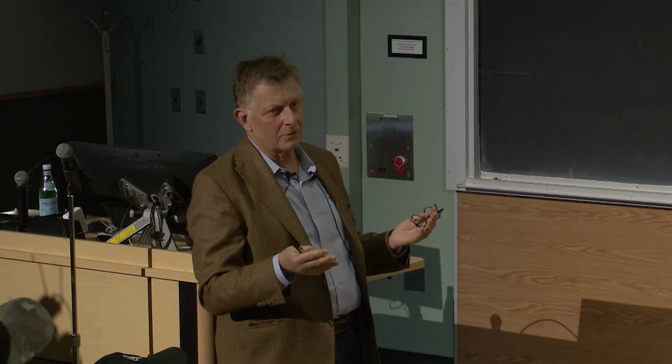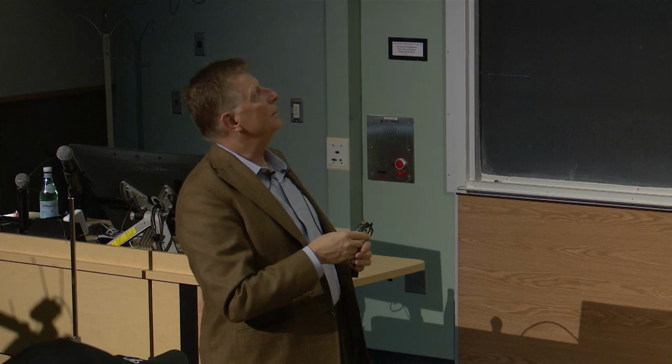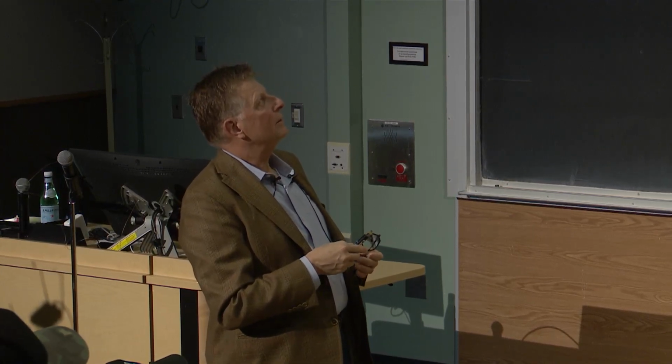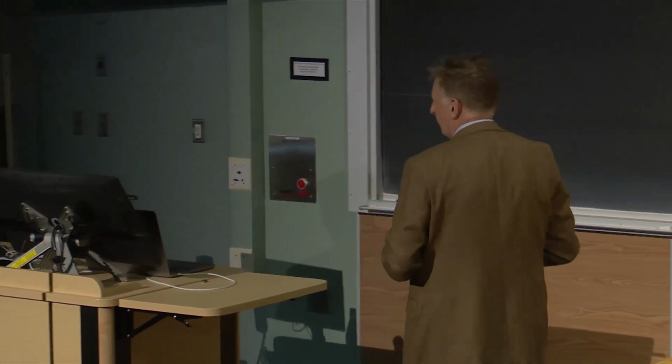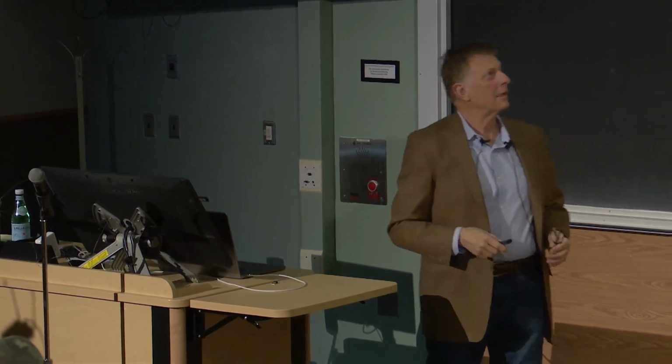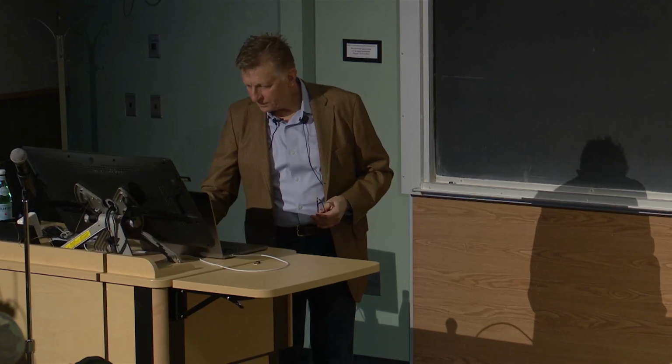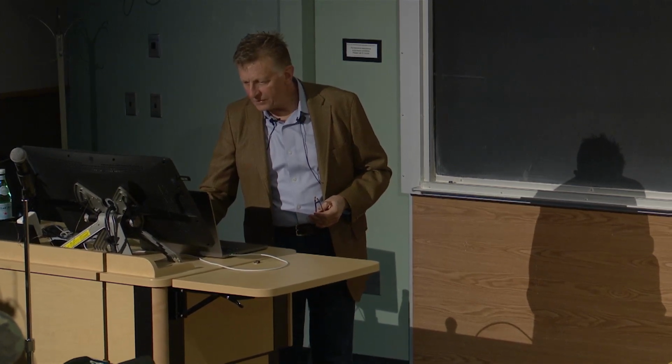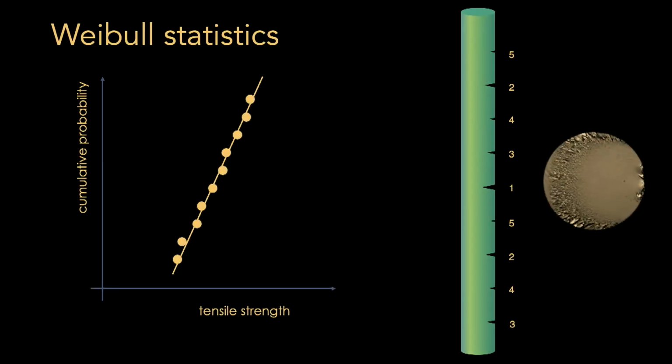That means I have a larger surface area per change in radius, and then eventually it starts to panic, and it creates this very rough surface, and there's more surface energy in that. Also, the crack velocity increases in the radial direction going away. It starts slowly, and then it accelerates to form more surface more rapidly. So this is what happens in glass. It's always the surface, and there's never a glass that breaks from the center unless there's a cavity in there to begin with.